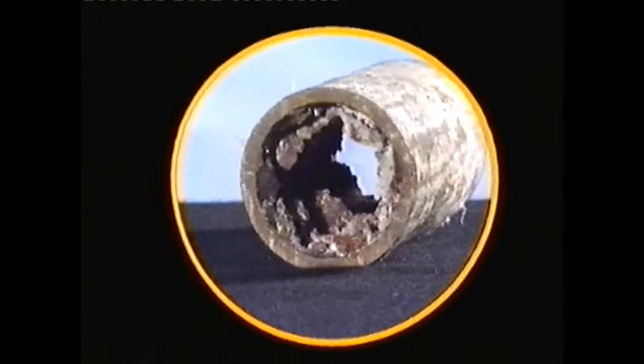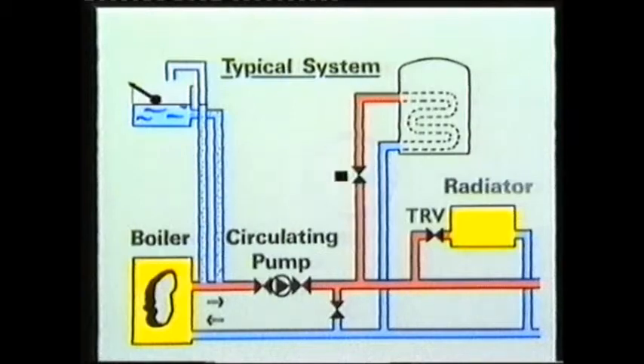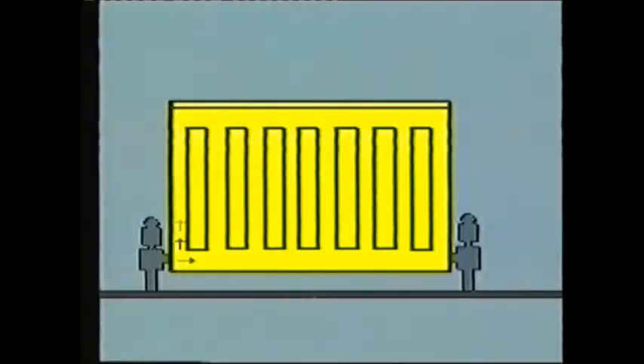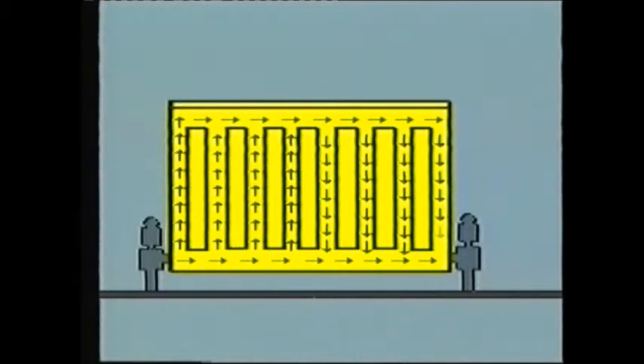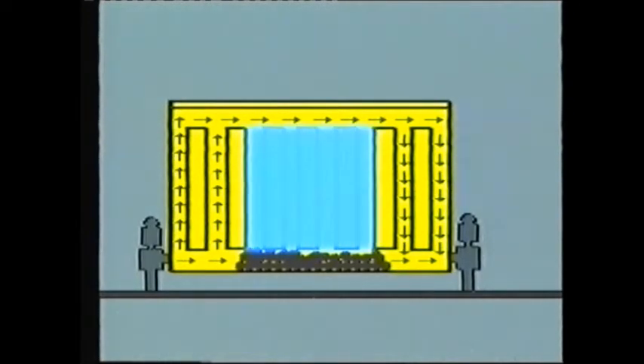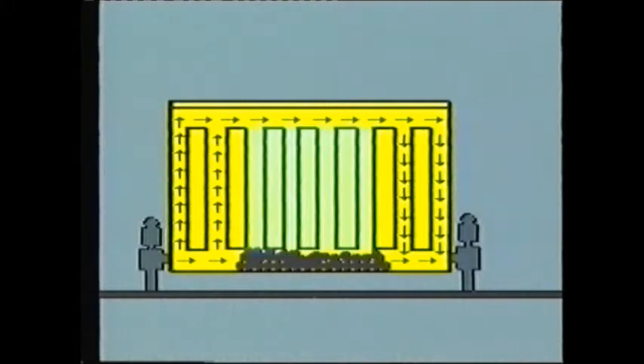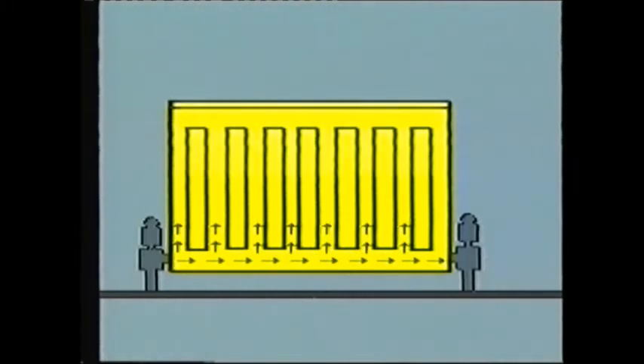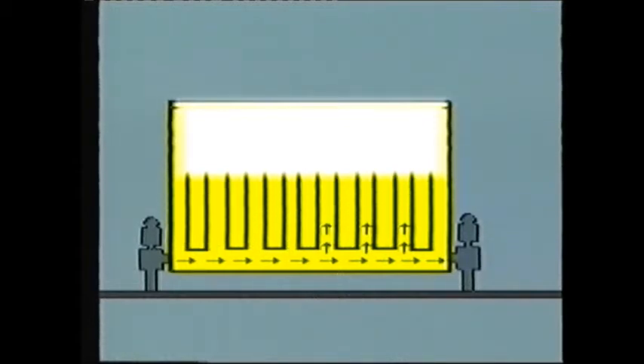Scaled pipework lowers the effectiveness of the system by restricting the water flow. And performance is further reduced by motorized and thermostatic valves becoming blocked with corrosion debris. Radiator output is also reduced as sludge accumulates at the bottom, restricting the water flow pattern and causing cold areas. And as a byproduct of the corrosion process, hydrogen forms, again causing cold areas. Because it collects at the top of radiators and necessitates frequent venting, it's often mistaken for air.